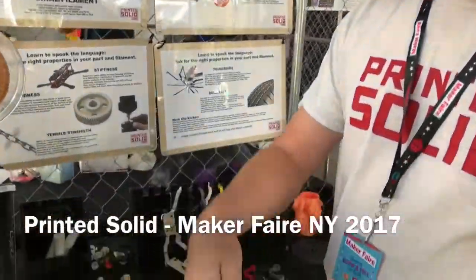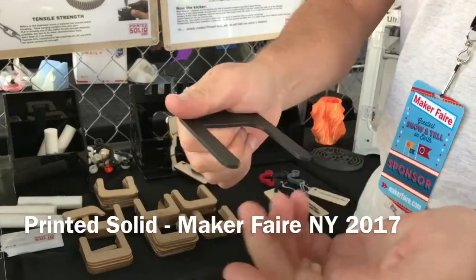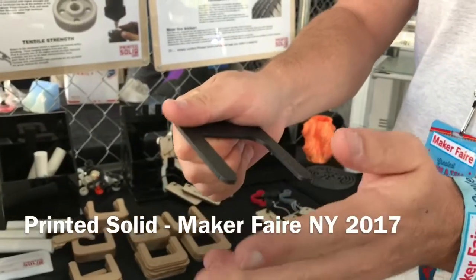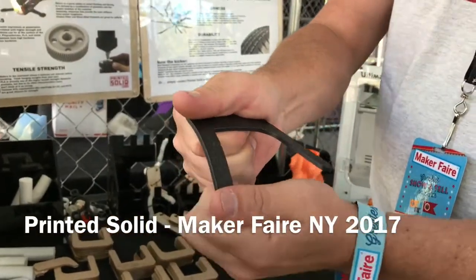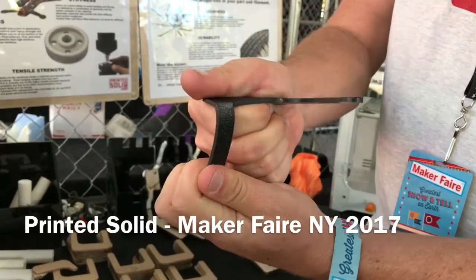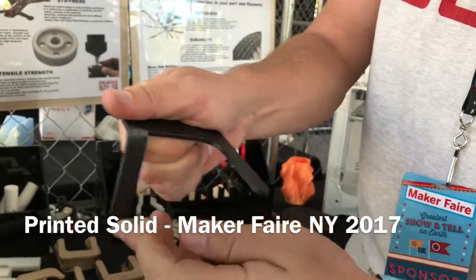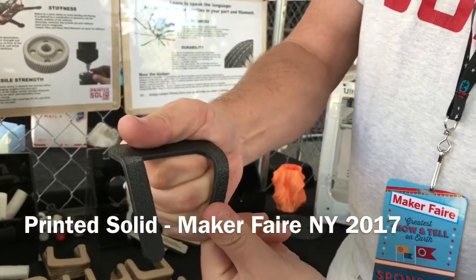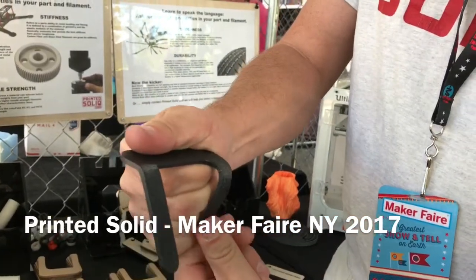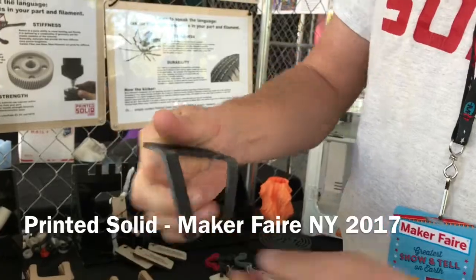Then if I take that same piece in ABS, which is a more ductile material, it's less affected by stress concentration. So if I try to break it, it's still going to break at that point. You can see it tearing here, but it's much harder. And if I try to break it where there's the fillet, it's not going to break at all. So things like that.